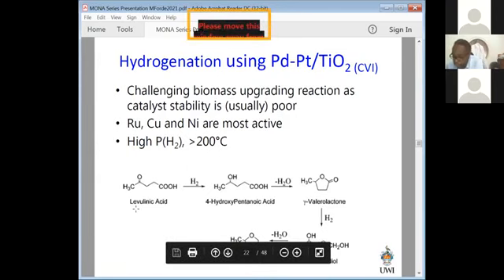So I'm going to speed up a little bit, time is running. The materials do really good hydrogenation chemistry as well, it turns out. So the same catalysts work for oxidation and hydrogenation, which is normally not the case in catalysis. The first reaction we looked at was levulinic acid, because it's one of those platform molecules that was on the top 20 list back in the day for biomass-derived molecules that have potential to replace molecules coming from fossil fuel-based resources, and in particular making gamma-valerolactone and obviously diols and MTHF, which is a fuel blender itself, or used for solvents, for production of cosmetic materials, etc.